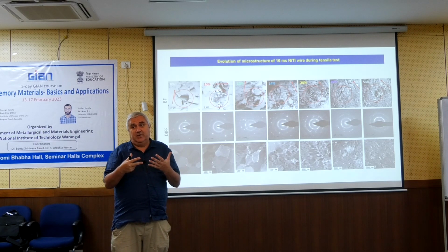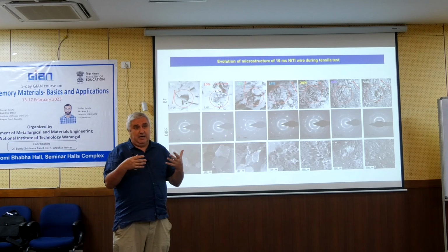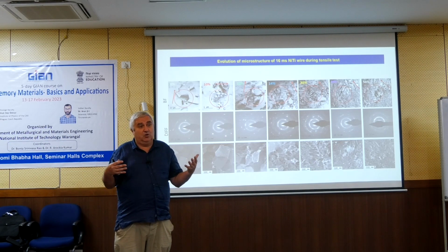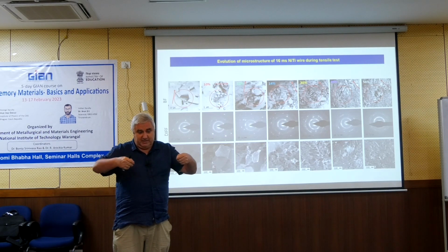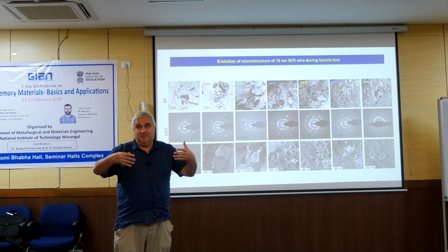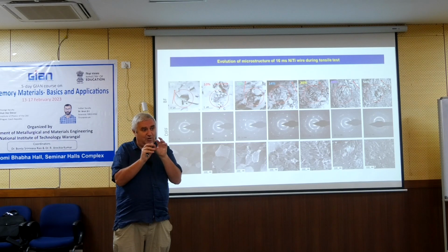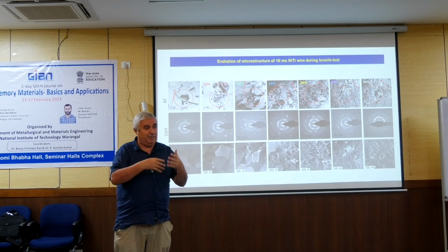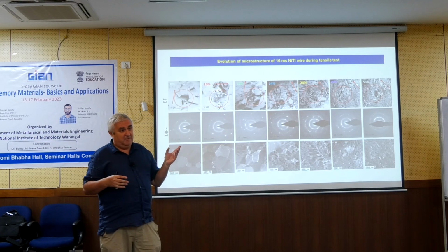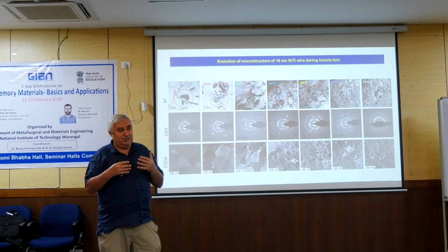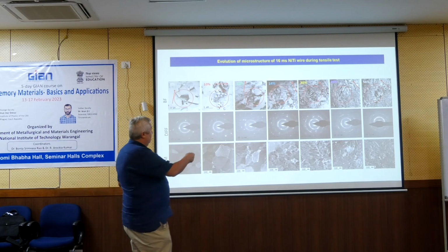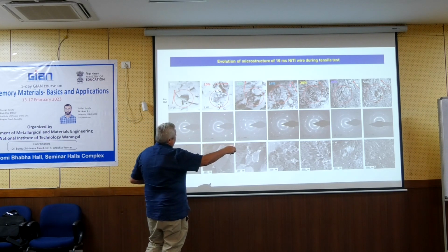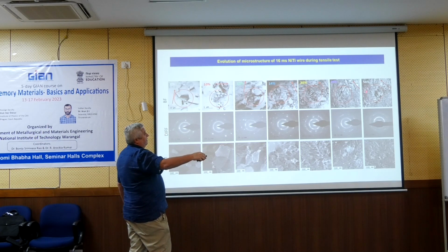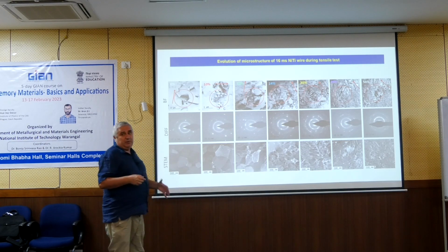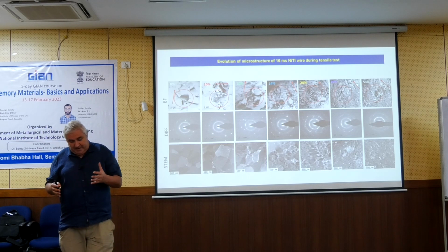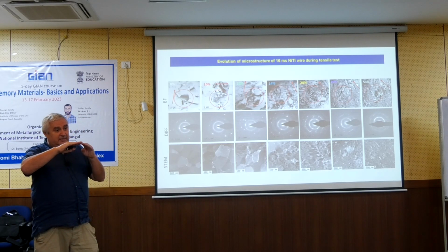With such a microstructure, the material is extremely hard after such deformation, and it is almost like after cold work. So if you deform the nitinol wire in tension, the mechanism of deformation makes it refine into small misoriented blocks, which is the same as what occurs during severe plastic processing. But here it is caused by the deformation mechanism itself. Because it rotates the lattice, like here we can still analyze it, as I will show tomorrow. But here it becomes so dense that even in conventional electron microscopy you can hardly analyze this, but you clearly see, and this process occurs at stresses like 1 gigapascal.